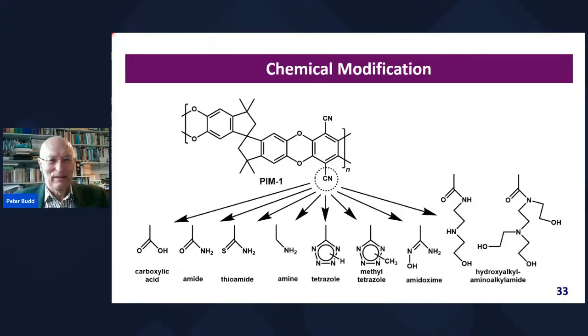Now, as well as adding things, if we have a polymer like PIM-1 as a good example, we have some nitrile groups on the backbone, and you can do chemistry on that. You can create all sorts of different functionalities. And this means that if you start with a base polymer, you can create actually a whole range of polymers that would be suitable for different types of separation or different circumstances. You can tailor the polymer for a particular separation through chemical modification. Sometimes you can modify the polymer and then process it into a membrane. Sometimes after modification, it's not processable, but it's possible to do the modification on a preformed membrane.